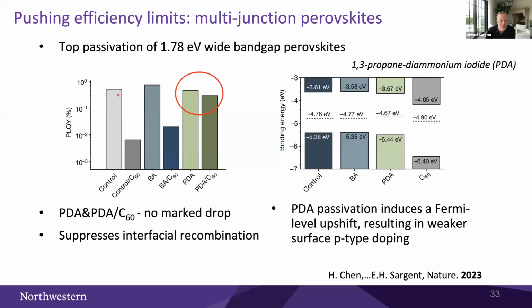And here too, the matter of loss of PL quantum yield upon the introduction of the C60 is a crucial issue. And some recent molecular searching has found that, for example, PDA, 1,3-propane diammonium, enabled a very significant reduction in the amount of quenching, consistent with reduced interfacial recombination. It also appeared from UPS studies to provide a beneficial upshift corresponding to weaker p-type doping, so kind of in the direction of a lightly n-type top surface.